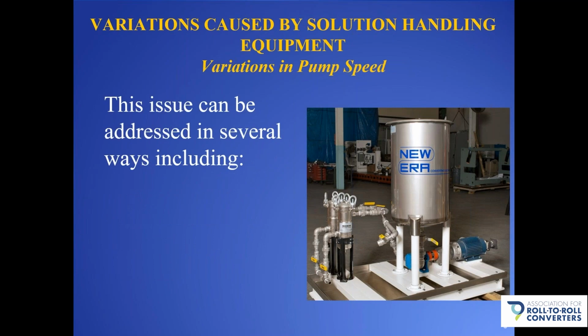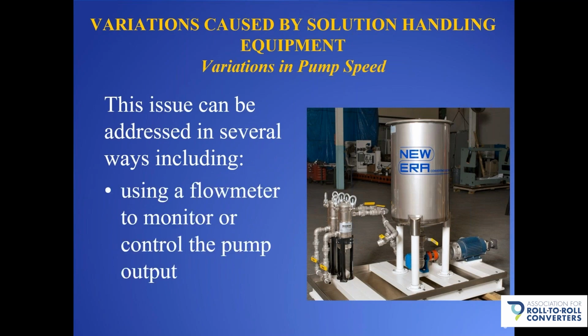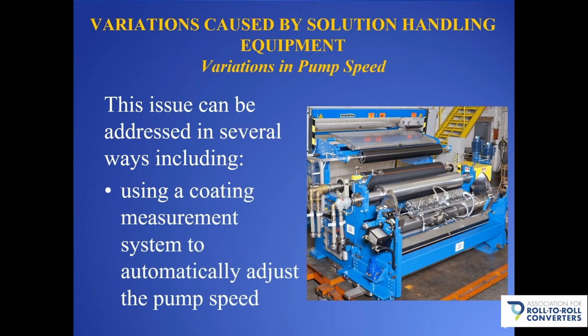So how do we address these issues? Well, we can use a flow meter to monitor or control the pump's output. Or as you see here, we can use a coating measurement system, a thickness gauge that will measure the coating laydown and automatically adjust the pump speed to compensate for these variations.